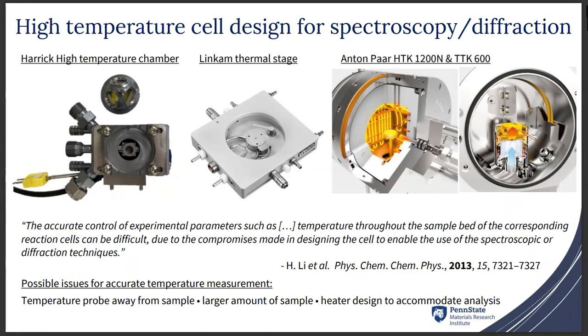In the middle, we see the Linkam stage, which allows high temperature analysis with a microscope, either FTIR or Raman. On the right, we see accessories from Anton Paar for high temperature experiments using XRD. One of the main issues with all this accessory is that there is always a compromise between the design of an accessory and the accuracy of the temperature we can achieve, because all this accessory needs to accommodate the spectroscopic or diffraction technique.